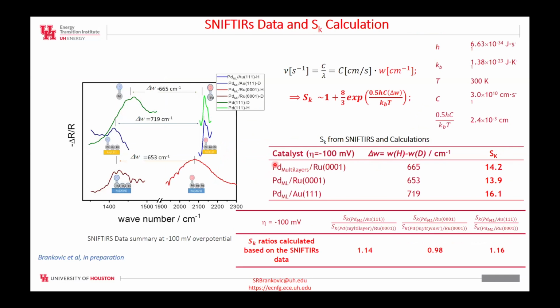And that's exactly what we do. And so the first thing that I want to prove to you is that the theory behind the separation factor definition is correct. So when we do spectroscopy of the hydrogen vibration bonds on these different catalyst surfaces, including bulk palladium, palladium on gold, or palladium on ruthenium, we record the difference between wave numbers of the vibrational bond for hydrogen and deuterium on each of these catalysts. And we convert the separation factor to its expression in terms of this difference in wave numbers by adding just a speed of light constant here to basically express the frequency as the speed of light over the wavelength of the light, and the wave number is the inverse of the wavelength. So basically this expression is relevant if we plug in here delta W, the differences between the wave numbers of the vibrational bond on these different surfaces or catalysts. So we do calculate the separation factors.